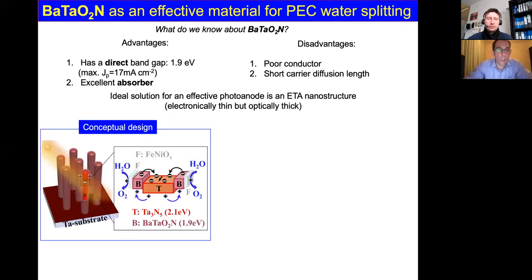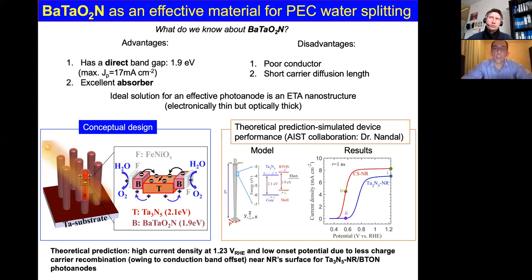Okay, so for that purpose, we again prepared the conceptual design. As you can see here, the location of the conduction band for the barium tantal oxynitride is lower, so that means the electron can be very easily passed. Then we asked the theoretical guy, with whom we collaborated at AIST, Dr. Nandal, and he simulated that model and showed the possibility that we can realize such a nanostructure, because the lifetime of the carrier is about 1 nanosecond, and he predicted high current density at this potential. Actually, this is the minimum potential which is required for the water splitting. As well as low onset potential due to less charge carrier recombination, owing to conduction band offset near the nanorod surface.